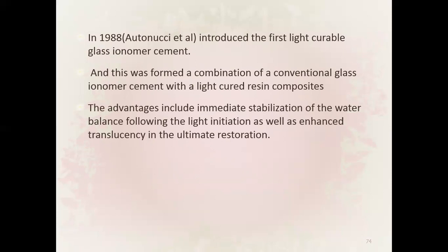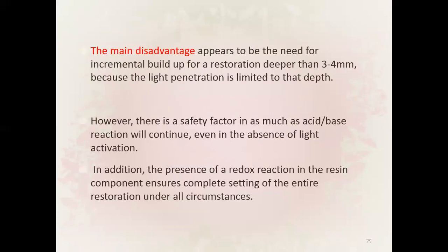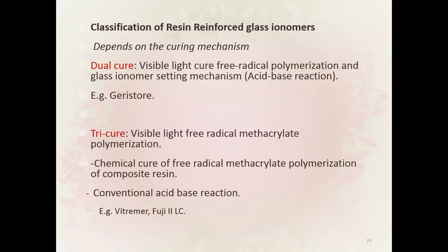The advantages included immediate stabilization of the water balance following the light initiation, as well as enhanced translucency in the ultimate restoration. The main disadvantage appears to be the need for incremental build-up for restorations deeper than 3 to 4 millimeters, because the light penetration is limited to that depth. However, there is a safety factor, inasmuch as the acid-base reaction will continue even in the absence of light activation. In addition, the presence of a redox reaction in the resin component ensures complete setting of the entire restoration under all circumstances.